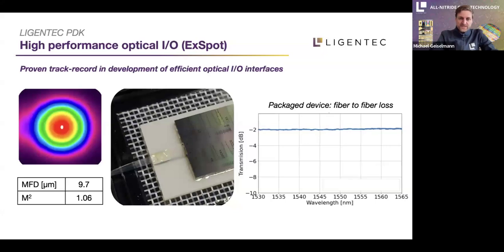Also a module that is very well asked for is the high performance optical I/O, where we have a proven track record in development of efficient optical I/O interfaces, where with this module we enlarge the mode field diameter on the chip to match an SMF28 mode field diameter of a fiber at 1550 nanometer wavelength. And when we scan around the wavelength here on a packaged device, so we couple a fiber to the chip, have a loop, and go back to the fiber, we get less than 2 dB in total coupling loss, fiber chip to fiber, with this module and the standard SMF28 fiber.